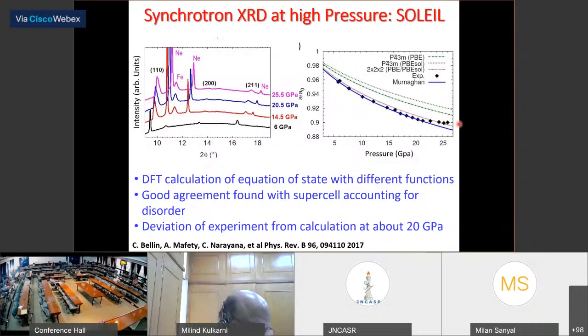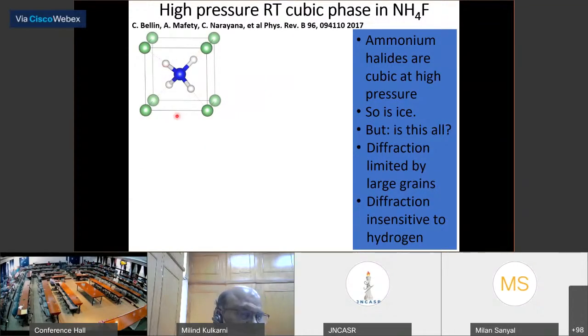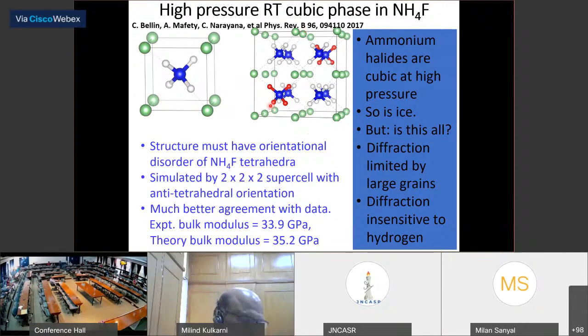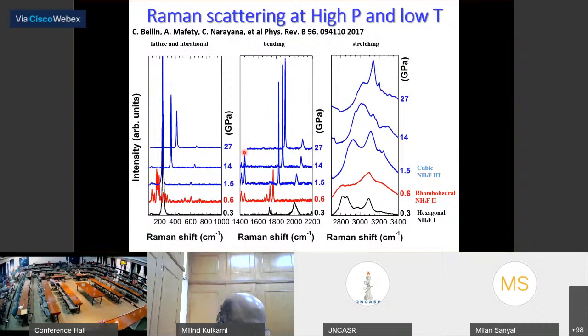Now, very interestingly, this is the data collected for the equation of state. When you want to fit it, you realize that in a DFT calculation you have to use a larger supercell instead of a cubic cell, and then introduce some distortions into the system. Then it can explain the system much better. If it is a disordered system and I expand the cell, I just bring in a tetragonal distortion into the supercell. That is what can explain ammonium fluoride's behavior in the equation of state, the deviation at 20 gigapascals.